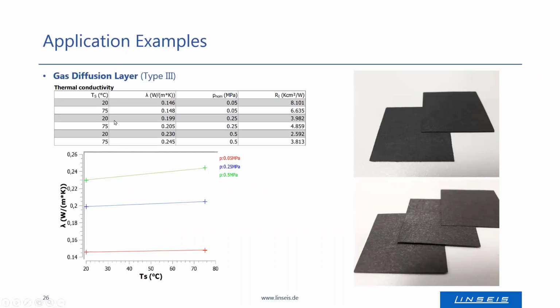Here are the end results, where one can see that with increasing temperature, the thermal conductivity is also slightly increasing. And one can see as well that with increasing contact pressure, the thermal conductivity also increases.